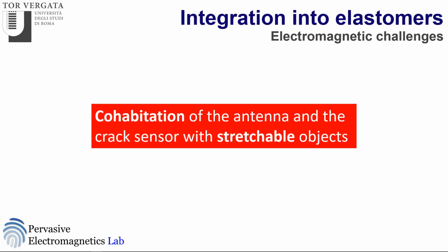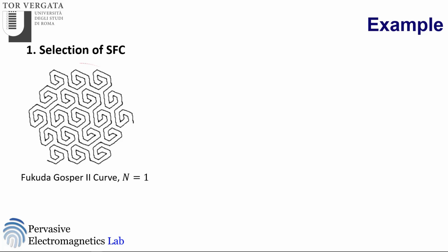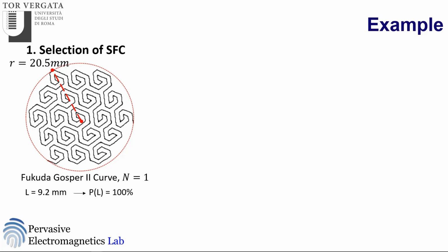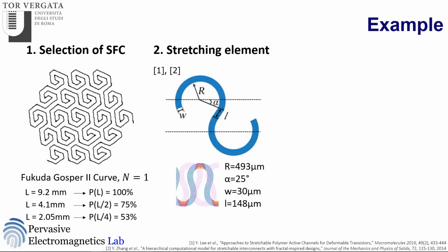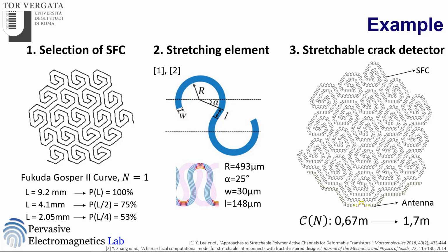The big issue here might be the cohabitation of the antenna and the crack sensor with a stretchable object. So, for instance, let's select the Fukuda Gosper II curve of first order, and let's choose a tile of 20.5 mm radius. Here I reported the crack detection probability for this configuration. Let's add a stretching element that gives the curve the stretching capability, and let's join all together. The first thing that we can see is that the curve's overall length is almost 3 times the starting length.